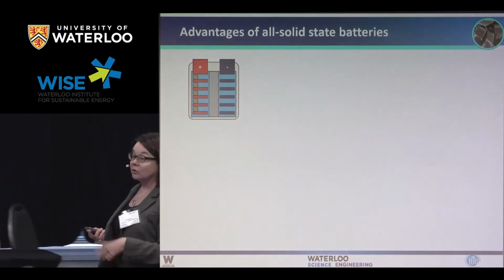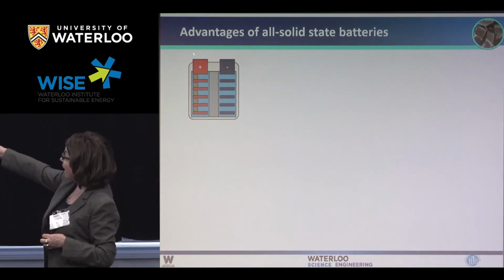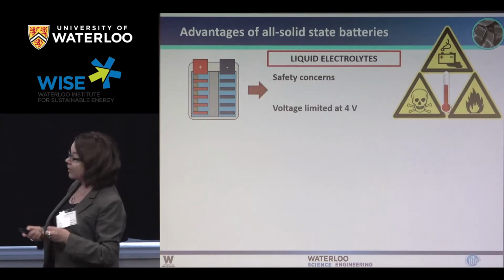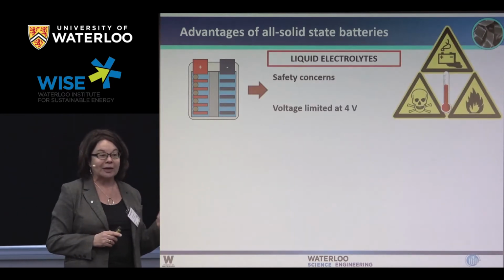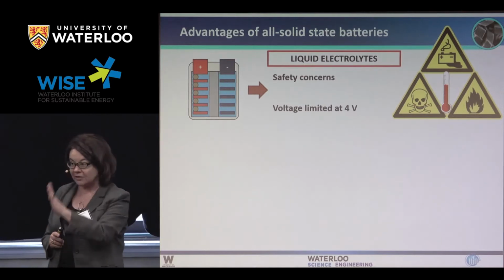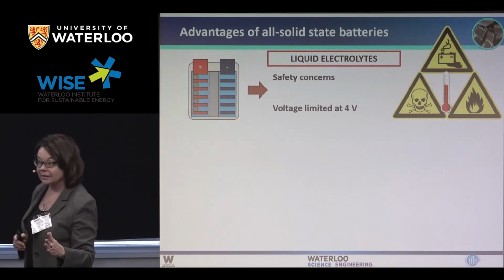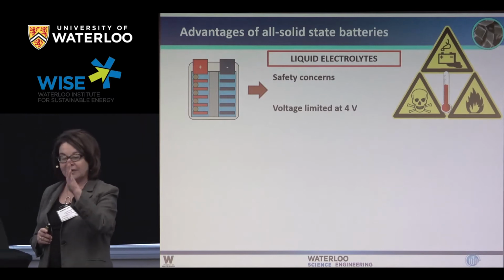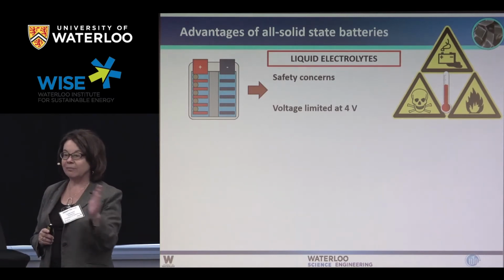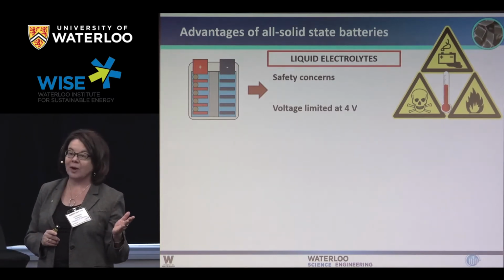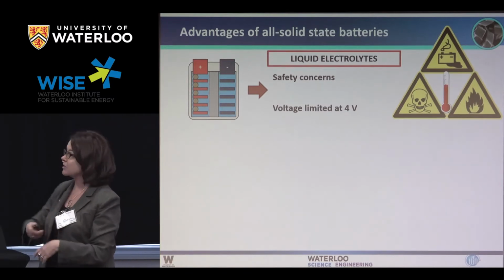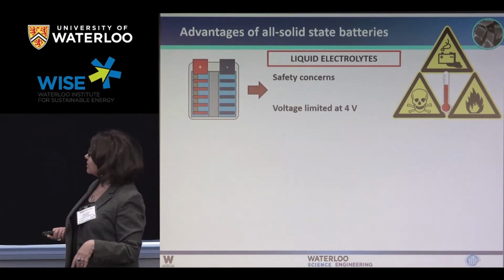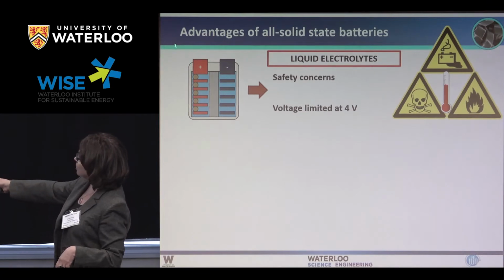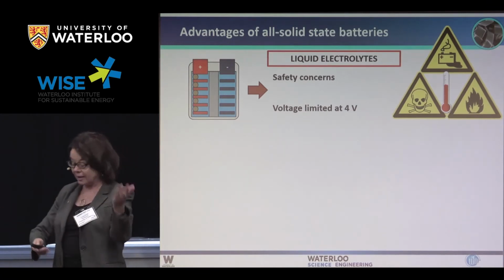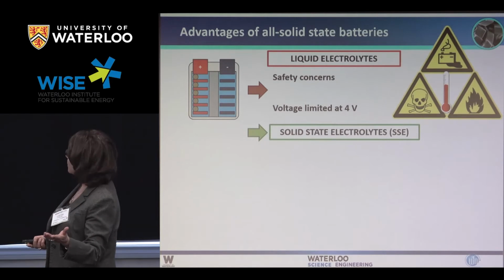So you take this normal-looking cell with your positive electrode, high redox, high potential, and your negative, low potential, and you then start to think about the problems of these liquid electrolytes. As I said, at the interfaces, those organic solvents react. And when they react, they form these very resistive layers that basically then ultimately cause thermal runaway in the cell because you can't get the current to pass through them. So these are serious safety concerns, and it means we can't push the potential of the positive electrode too high, otherwise these organic materials decompose.